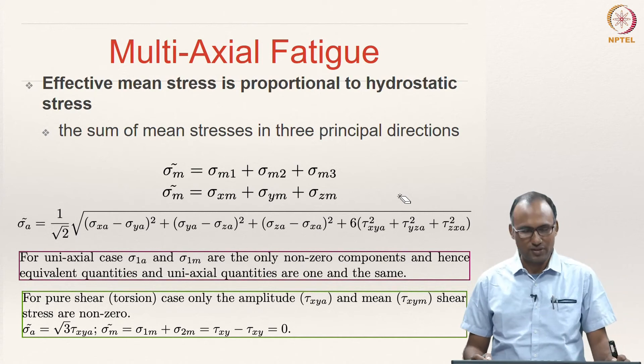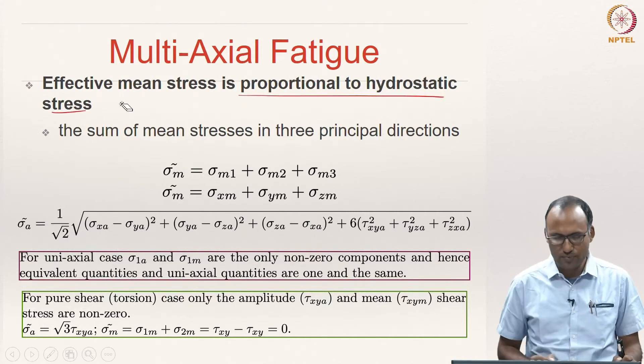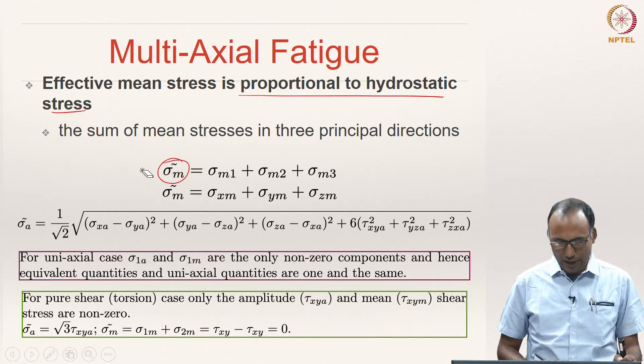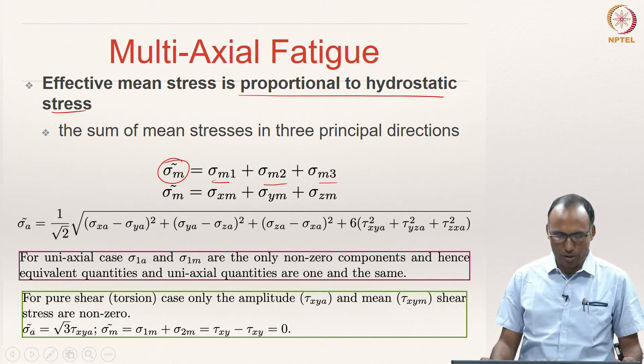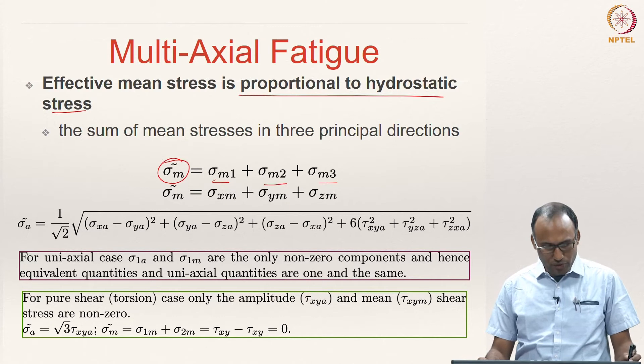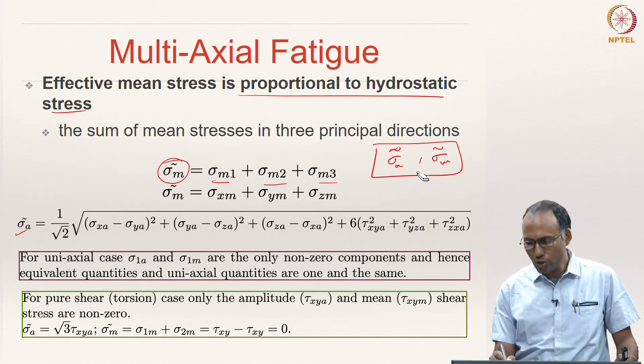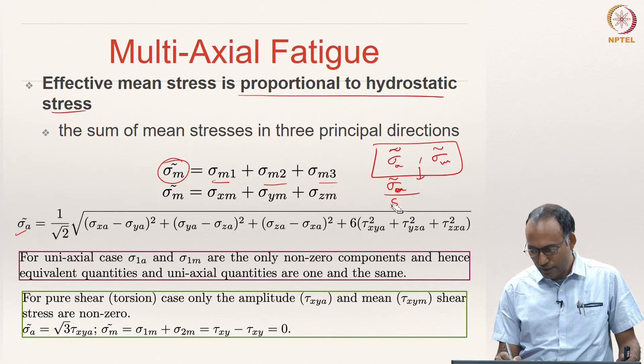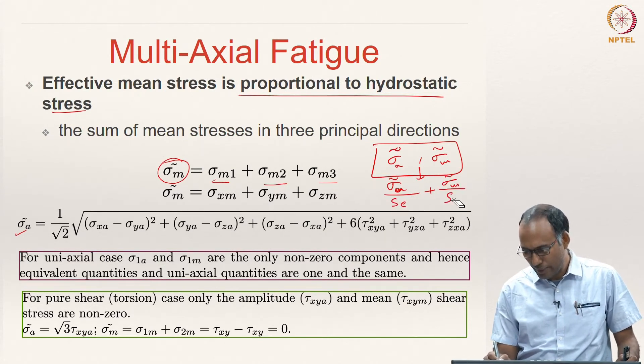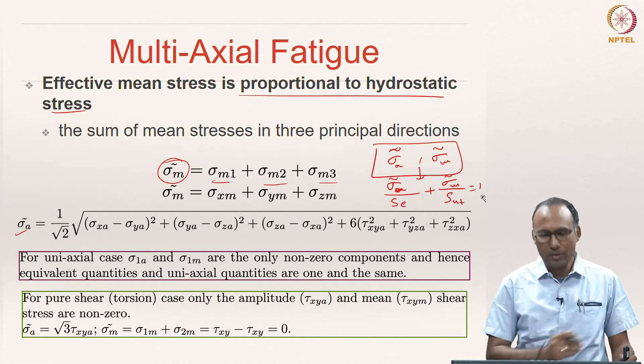However, if you also have mean stress, the effect of mean stress is to be taken into account. It is known that the effect of mean stress is proportional to hydrostatic stress, and hence equivalent mean stress can be calculated as the sum of the three principal mean stresses: sigma m1 + sigma m2 + sigma m3. That is your equivalent mean stress. You can thus calculate the effective stress amplitude and effective mean stress, and once you have these two things, you can use the Goodman criterion: sigma a tilde / Se + sigma m tilde / Sut = 1, and solve the problem exactly the same way as before.